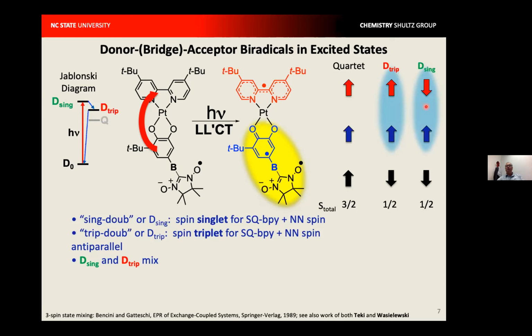So in these 3-spin excited states with catecholate donors, we have a quartet and then two different kinds of doublets. We have a D-trip, where the chromophore semiquinone bipyridine is in a triplet state, antiferromagnetically interacting with the nitronyl nitroxide radical, and the D-sing, where the chromophore is in the singlet excited state, coupled with the nitronyl nitroxide radical.